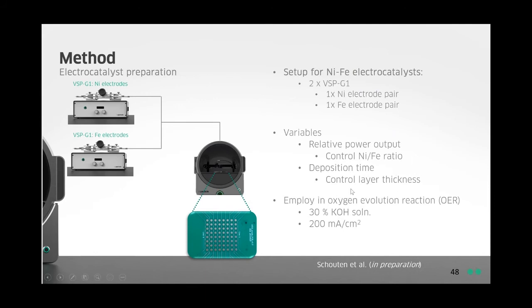In addition, by varying the deposition time, we could control the layer thickness, and the electrochemical cell was then used for the oxygen evolution reaction with 30% KOH solution and a current density of 200 milliamps per square centimeter.